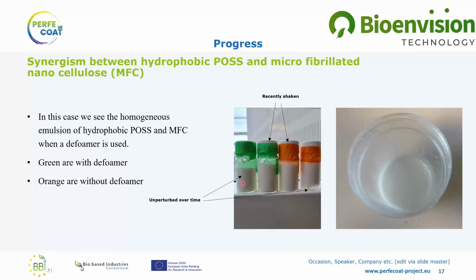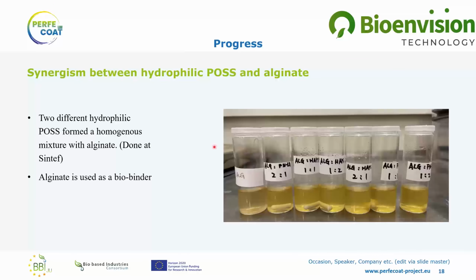And as you can see, the mixture without defoamer already separates, while the one with the defoamer is stable, forms a stable emulsion. And this is just a top view of the emulsion. The next test was the synergism between hydrophilic POSS and alginates, which was done at SINTEF.